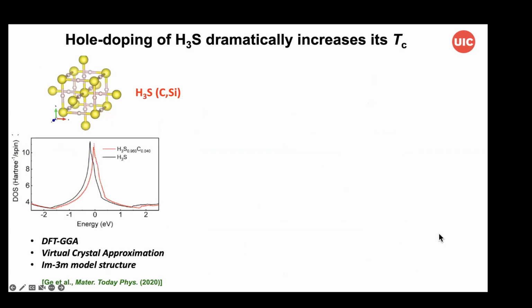So in looking at the mechanism, we took the notion that perhaps one has some kind of doping of carbon, and if you consider other dopants such as silicon or phosphorus, the same physics and chemistry would emerge. In the case of carbon and silicon here, what's needed is to somehow shift the Fermi level relative to the peak in the density of states that's just offset from the Fermi level in the pure H3S system. And this offset appears in basically all the band structure calculations for H3S.